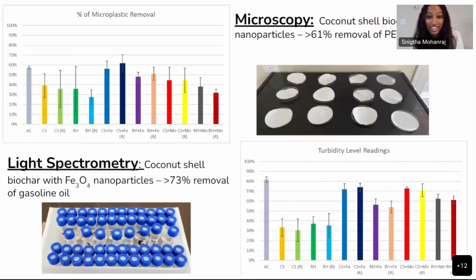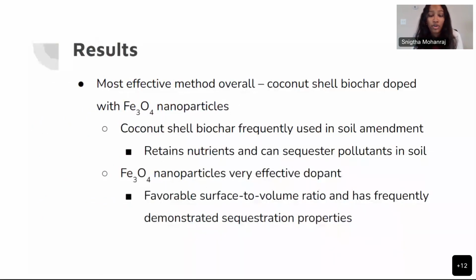And then in the microscopy, which is the second analysis, the coconut shell biochar with iron oxide nanoparticles, again, had the highest removal rate of the PET microplastics, removing over 61%. And in the light spectrometry, again, the coconut shell biochar with iron oxide nanoparticles removed roughly 73% of the gasoline oil. And so overall, the most efficient method was achieved through using coconut shell biochar doped with iron oxide nanoparticles.